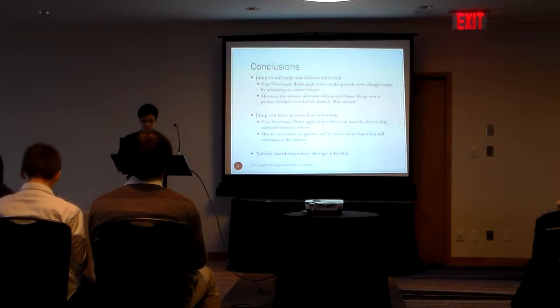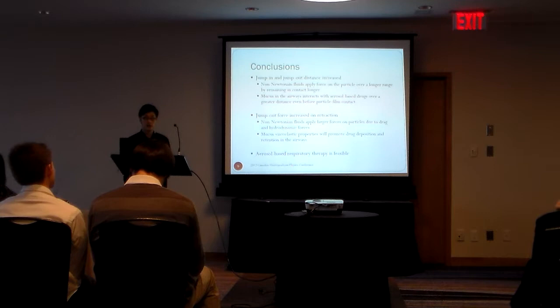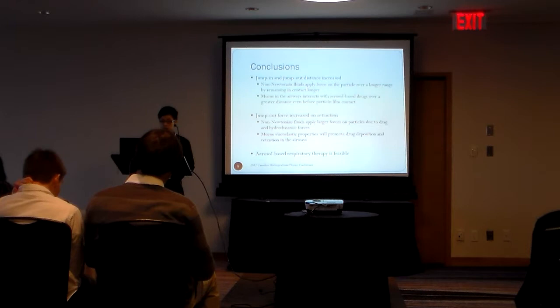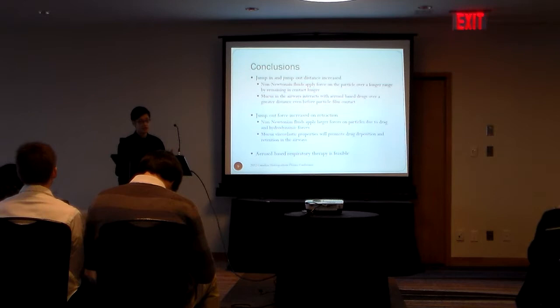These results are part of the broader model for how drug particles interact with the mucus layer, and they can be summarized in two main points. First, the jump-in and jump-out distance increased in the non-Newtonian sample, meaning the viscoelastic fluid applies a force on the particle over a longer length scale and remains in contact for a longer time. The mucus layer therefore strongly interacts with aerosol-based drugs, pulling the particle into the film at a greater distance even before contact. Second, the jump-out force increased on retraction, providing evidence that non-Newtonian fluids apply larger drag and hydrodynamic forces on particles.